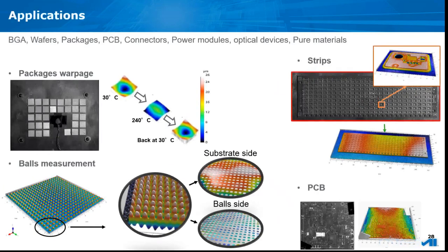So there are different applications where the tool can be used, such as package warpage measurement. We can measure up to 30, 40 different packages during a reflow. We can see in the photo here the shape variation between room temperature, 30 degrees C, then 240 degrees C, and then back at 30 degrees C. So we can see the shape evolution, and we also have the warpage graph that allows us to characterize the different samples.